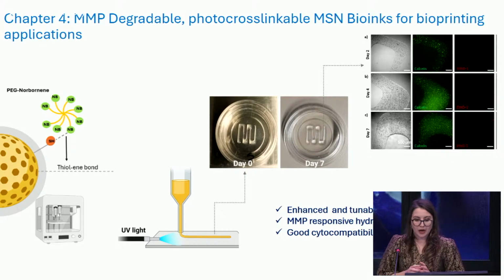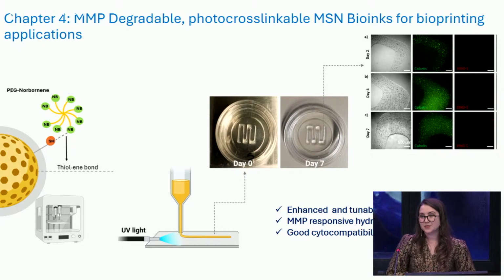In chapter 4, I developed nanocomposite bioinks specifically tailored for extrusion-based 3D printers. In the system, thiol-functionalized MSNs form a robust, stable hydrogel network with norbornene-functionalized PEG polymers through UV-initiated thiol-ene interactions. Different from other chapters, here I modified the MSN surface with MMP-degradable peptides, which allow cells to remodel their environment by secreting MMP enzymes and degrade the hydrogel network.